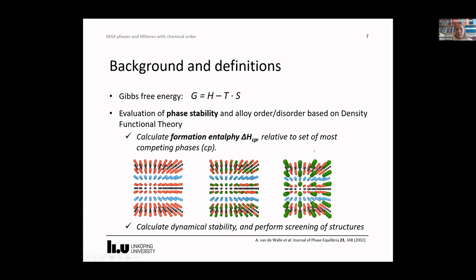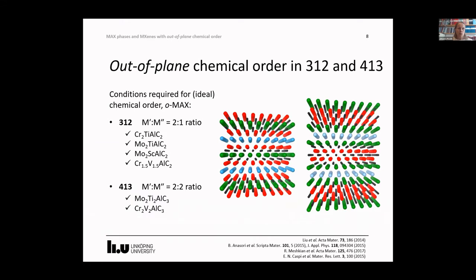And this is what a chemically ordered configuration can look like. And when we have a result like this, we also calculate dynamical stability. In other words, how stable this structure is with respect to lattice vibrations. We also perform screening of structures, more than 1,000, to ensure that we indeed have the lowest energy structure for a certain stoichiometry. But let's start to talk about chemical ordering in MAX phases.